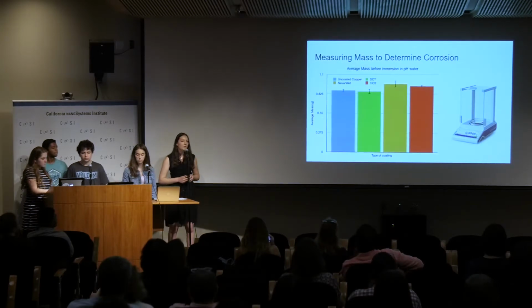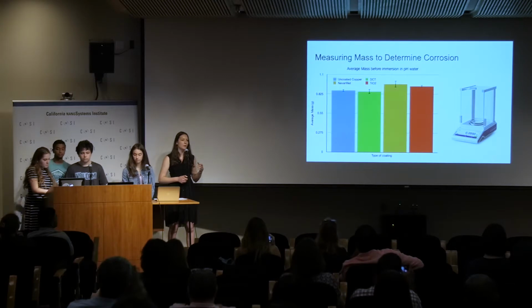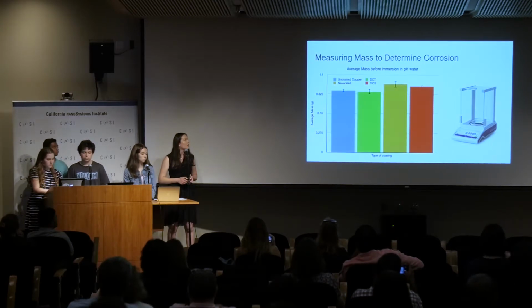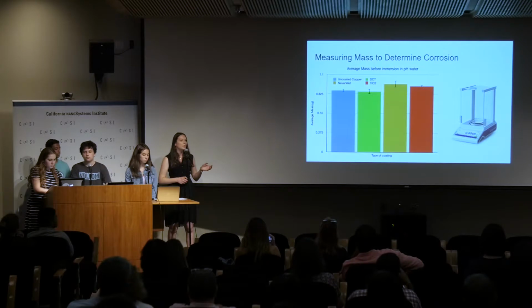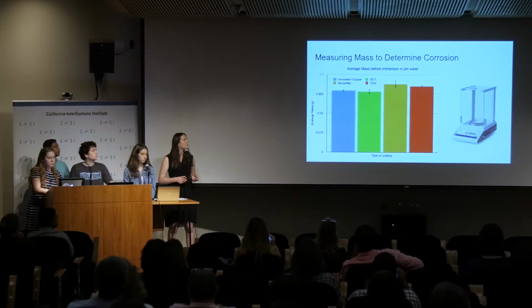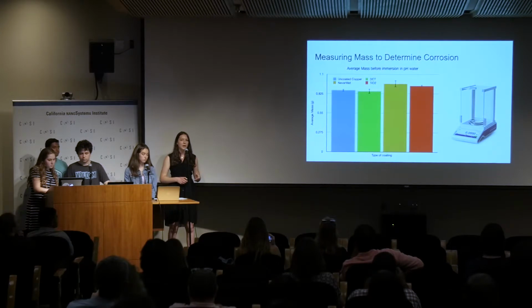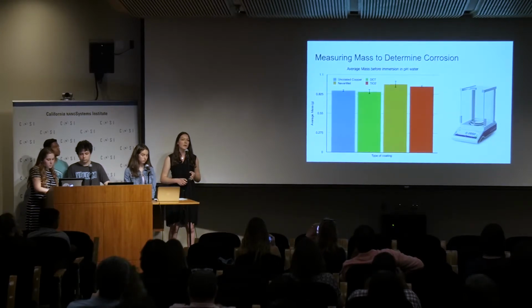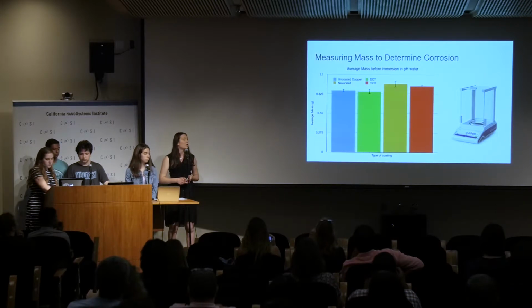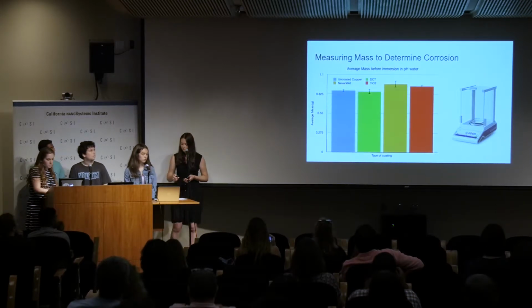And we also measured the mass to quantify the corrosion. And as we can see, the uncoated copper, because it has nothing on it, has a very small standard deviation. But the Never Wet, because it was a spray, the coating was uneven, and that caused the standard deviation to be quite large and maybe affect the results.